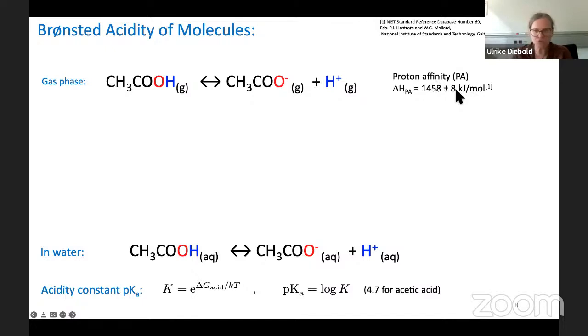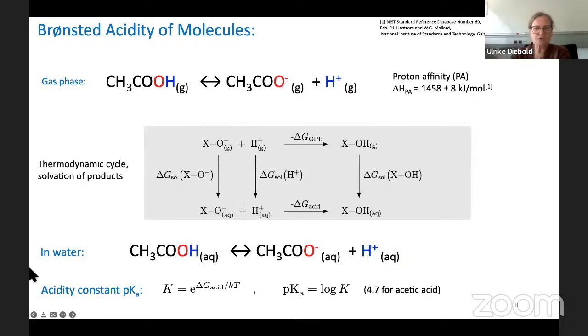It's tabulated for most common molecules, and it has to do, of course, with the acidity, right? Because if it's easy for the molecule to give off the proton, then it's more acidic. If it's harder, then it's more basic. And these two are related in some sort of thermodynamic cycle. We have here the change in the Gibbs free energy when this proton is separated or not, and then you have the same thing in aqueous solution, and then you have the solvation of these. You can go around in this cycle if you take each of these fragments and dissolve it, and then somehow determine this delta G of the solvation. So those are the two things that are connected.